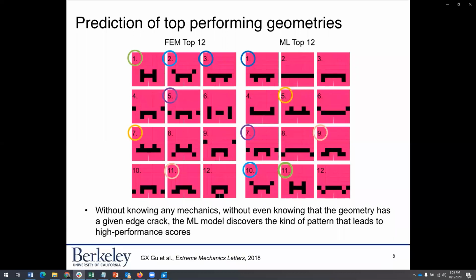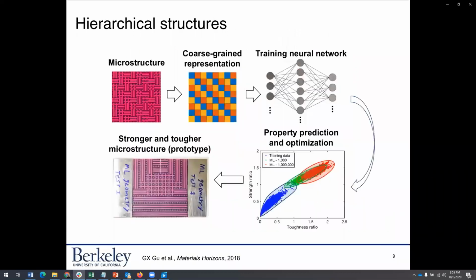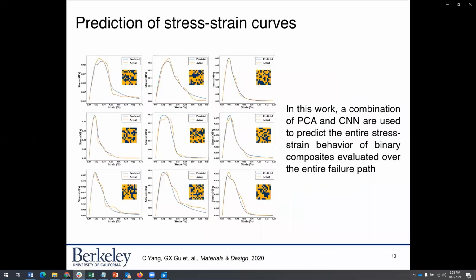And now we have expanded on this work and have shown how we can actually use deep learning models to predict the actual properties of various hierarchical composites rather than just classifying them as a good geometry or a bad geometry. And we have also validated our results using additive manufacturing and mechanical testing. Now, beyond predicting material properties, we have shown that if we combine principal component analysis and convolutional neural networks, we can predict the entire stress-strain behavior of composites evaluated over the entire failure path.